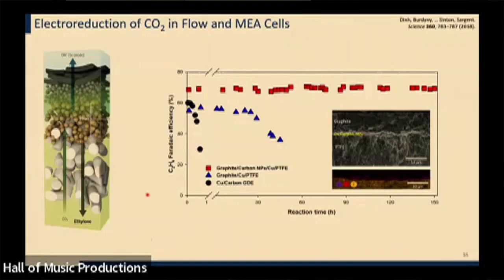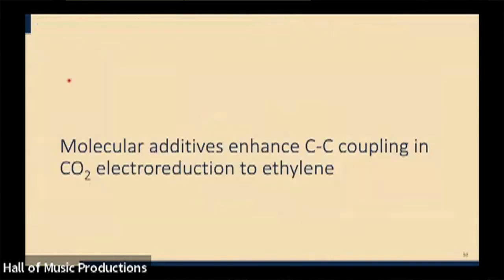And only once we did that would we be in a position to then start to systematically vary the catalyst composition. So this we did on a gas diffusion electrode, something that allowed the gas phase CO2 in through the back, allowed it to come into contact with a solid heterogeneous catalyst. This one's showing copper nanoparticles. And for that to be in contact with a liquid electrolyte. So really a three-phase boundary being formed between the gas and the solid and the liquid phases.